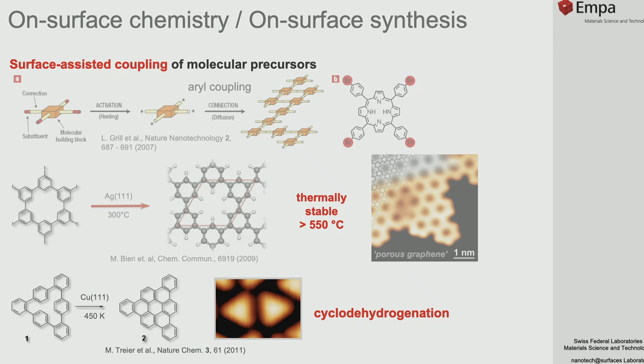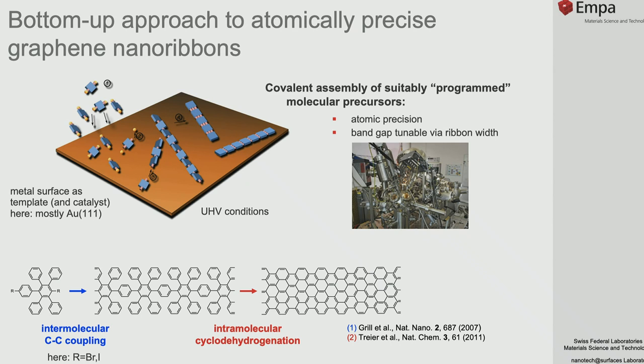Our next step was to study cyclodehydrogenation reactions—how we can go from a molecule that looks like a patch of graphene with missing carbon-carbon bonds to a complete graphene patch. The formation of internal carbon-carbon bonds and removal of passivating hydrogen atoms is driven both by van der Waals interactions with the metal substrate and by a moderate catalytic activity of the substrate. Combining all these ideas, Fasel and Ruffieux succeeded: a molecular precursor with a cleverly designed shape and halogen-saturated anchoring points, when deposited on a noble metal substrate, self-assembles into polymers, and upon increasing temperature, cyclodehydrogenation yields the nanostructures.